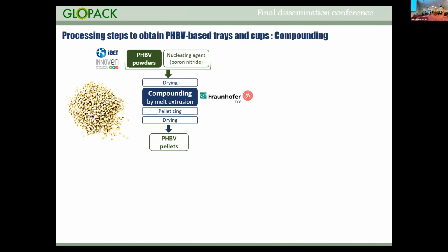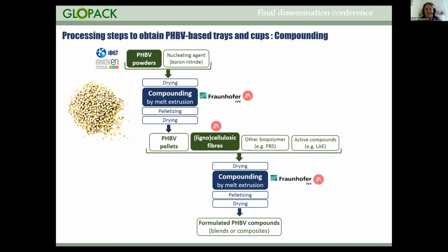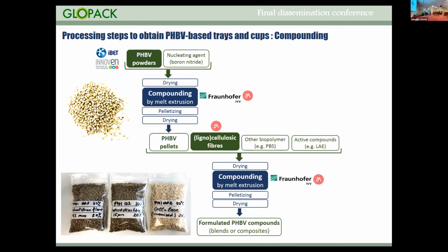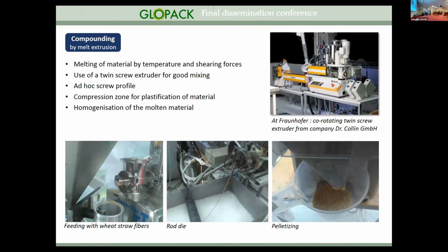The first processing step is to produce some PHBV pellets by mixing these PHBV powders with nucleating agents, for example, boron nitride, because one first bottleneck of PHBV is a very slow crystallization. So if you want to process some material, you have this first compounding step. Then you have a second compounding step, if you want to mix this PHBV with additives such as lignocellulosic fibers or other biopolymers to produce some blends, or active compounds to produce some active packaging. This compounding step will be developed by Cornelia.